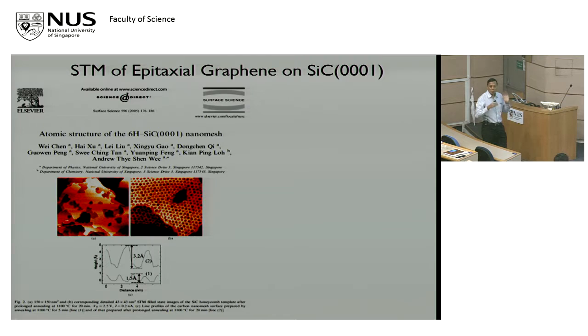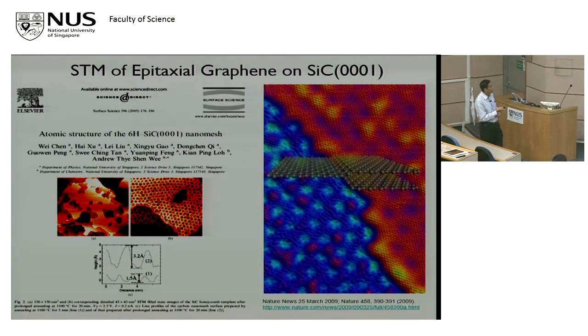But of course, the paper didn't focus on that because in 2005, we hadn't read about the first few graphene papers, which came out in 2004. But within a year or two, we realized, why don't we work on epitaxial graphene, as this graphene is called because it's grown epitaxially on top of silicon carbide? Why don't we work on this area since we have been working on it all along, but we were doing something else with it. We were using this as templates to put molecules into the holes, which we did, fullerene molecules in holes, which was very interesting. But we switched and we focused on the graphene layer that forms on top of the nanomesh.